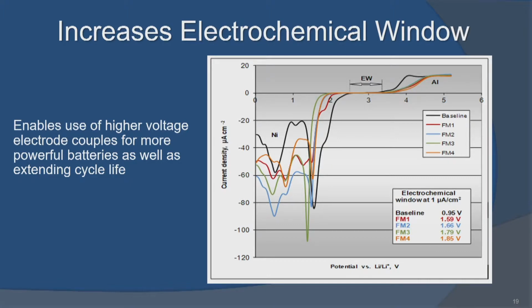One of the most important points, and it's kind of hard to get, is it increases the electrochemical window of stability. Now what this means is all batteries, when they're fully charged, they're at a very high voltage, and when they're fully discharged, well, your voltage is gone because your charge is gone. Organics have a very narrow electrochemical window of stability. That means when your battery is very, very charged, or even more importantly, very, very discharged, electrically, the organic begins to degrade, which leads to early battery deaths. Because we have a more robust inorganic system, our window is much wider, leading to much longer lifetimes and a safer operation during those charge and discharge cycles.